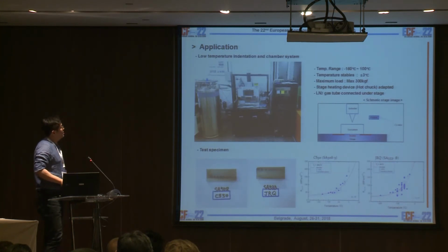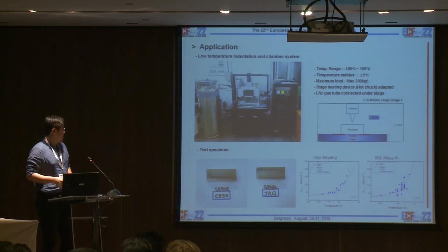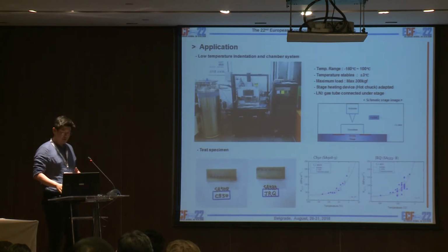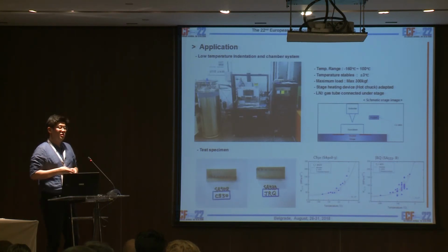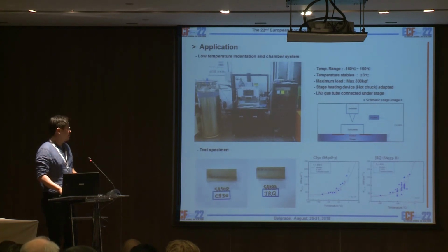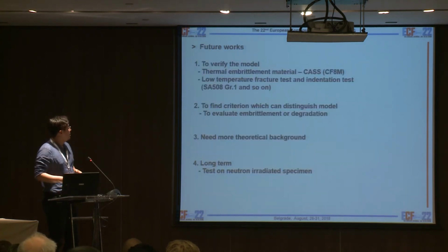As an application, last year we set up a low temperature indentation chamber system to test at low temperature. And the Korea Atomic Energy Institute provided us a special specimen, which was used in the master curve method. So the data are on the right side over there, but unfortunately there was no transition behavior in the indentation test. But we try to find T0 as the ductile brittle transition temperature. And future work remains to verify the model.